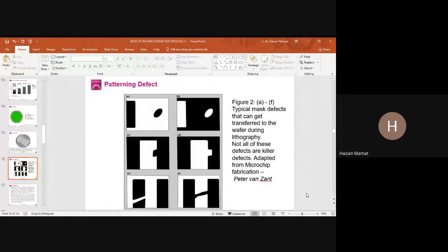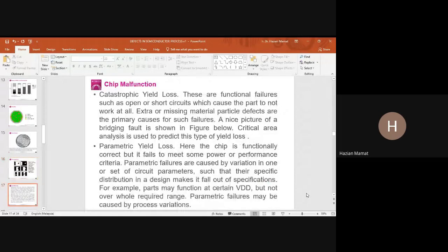Okay, chip malfunction. Catastrophic yield loss: there are functional failures such as open or short circuits which cause the part not to work at all. Extra or missing material particle defects are the primary cause of such failures. The features of the bridging fault are shown after this. Okay. Critical area is used to predict the type of yield loss. Okay, this is the bridging defect.